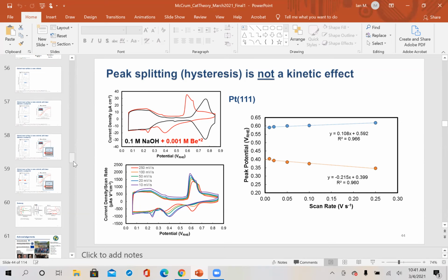I'll briefly mention, yes. We've seen similar effects on other pure metal single crystal electrodes, and we're working on explaining those effects. Both effects where we see this exchange between adsorbed hydrogen and adsorbed hydroxide. So this is not a phenomenon just for platinum steps. Any surface that binds both species strongly will show this exchange. And on those surfaces, we then also see pH effects and cation effects. They're roughly similar to what we see with platinum, but we're working to see if it's really the same.